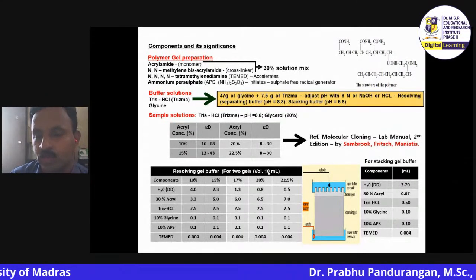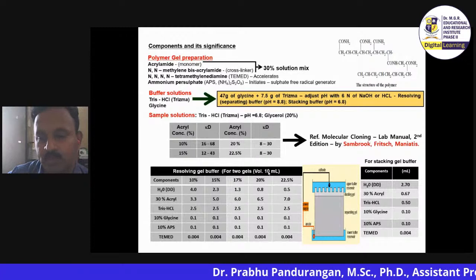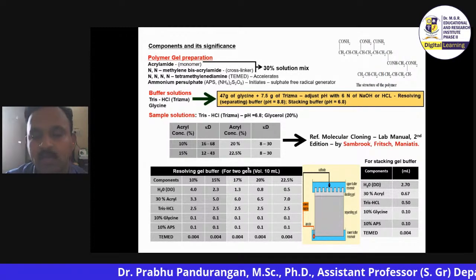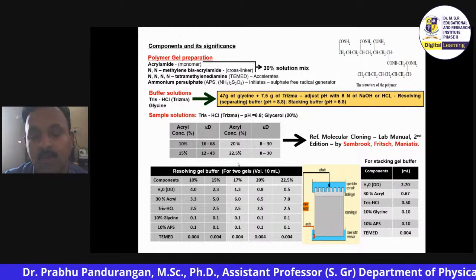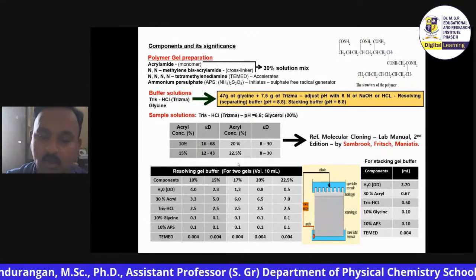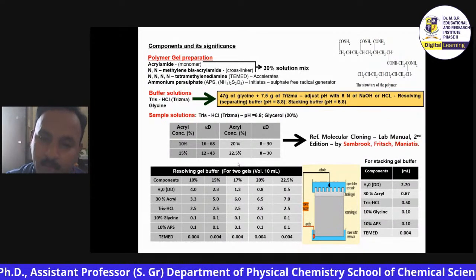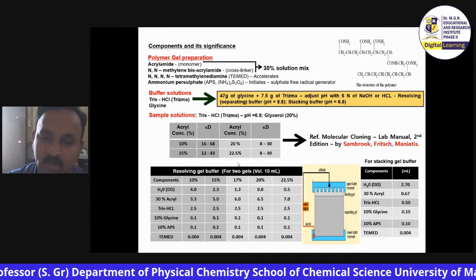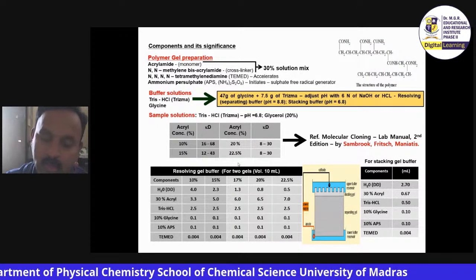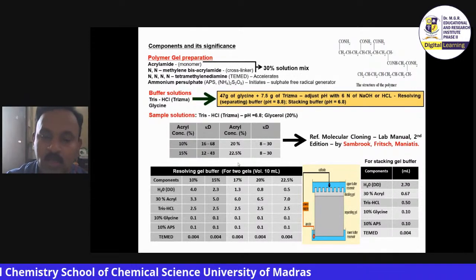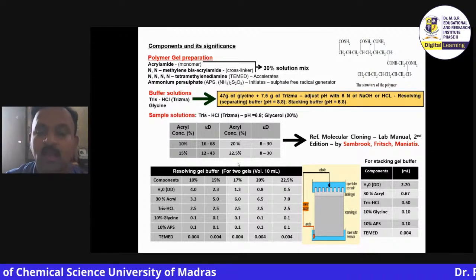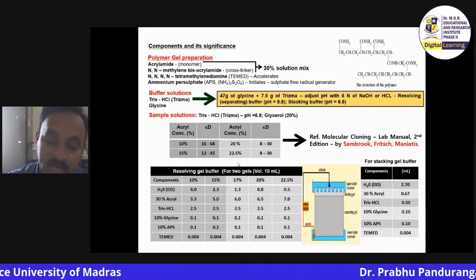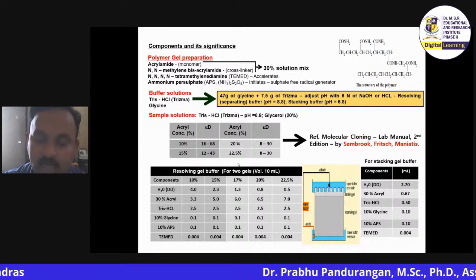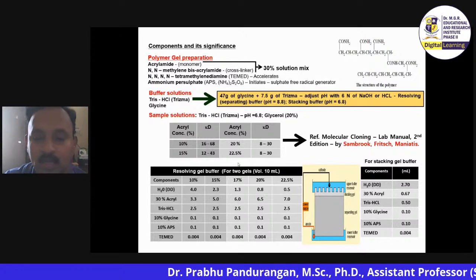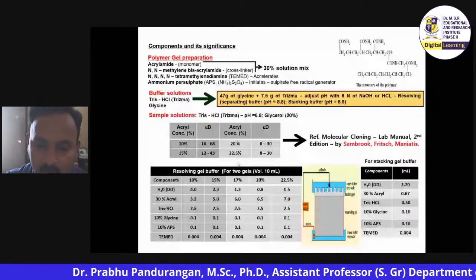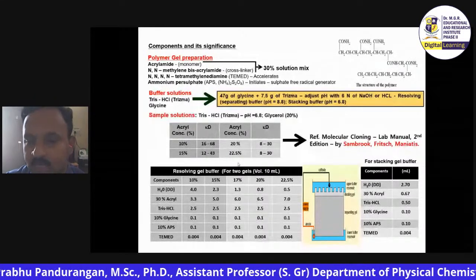If you tune the percentage of gel making with the constituents available here, you can separate clusters. But here the problem is yield. You will not get a higher yield with this technique, but you will not miss out a small cluster from this crude sample. In solvent fractionation, you will miss out the very small new clusters, but there you will get a higher yield. Whereas here it is a greener technique, the yield is low, but certain new compounds, new particles can be isolated by this technique of PAGE.